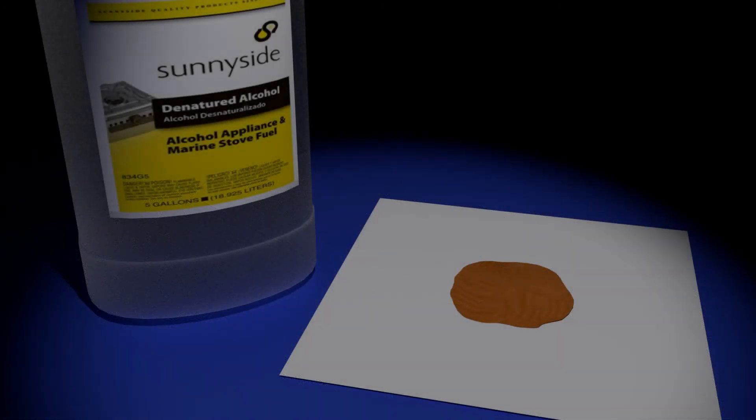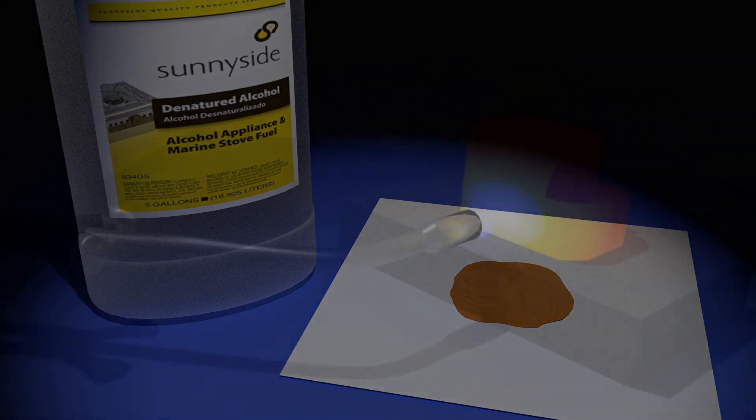Wrap your gold powder in jewelers tissue paper. If that is not available, you can use a small section of a paper towel. Soak the wrapped gold powder in alcohol and place it in your crucible. The paper and alcohol will help secure the powder so that the air currents produced by the torch flame don't blow it away. Both paper and alcohol will burn away, leaving no trace.